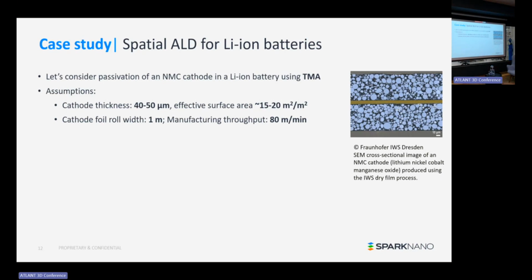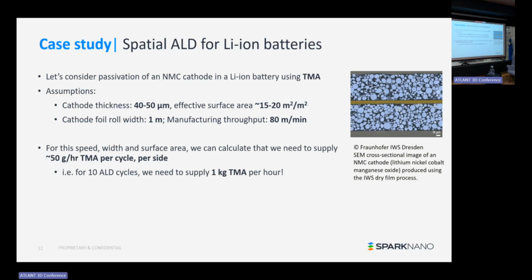Some assumptions: we expect that the cathode thickness is 40 to 50 microns, which corresponds to an effective surface area of, let's say, somewhere between 15 and 20 square meters per square meter. We go for mass production, so it's a roll-to-roll process, 1 meter wide rolls, 80 meters per minute web speed, and of course we have to go double-sided because that's what these electrodes look like. If you then do the math for this speed with this surface area, we need to supply around 50 grams of TMA per hour per ALD cycle per side. So double-sided, 100 grams per hour. And if you want to do 10 cycles, you need to supply roughly 1 kilogram of TMA per hour.